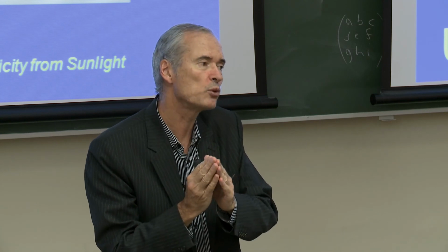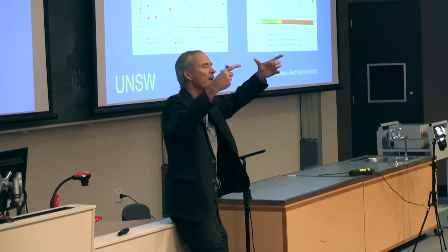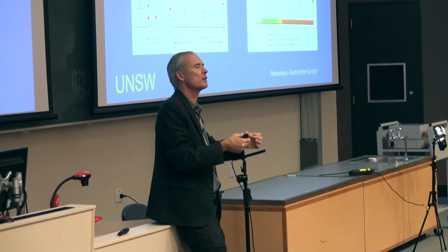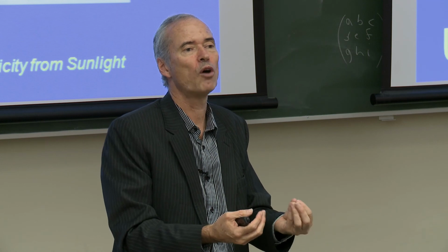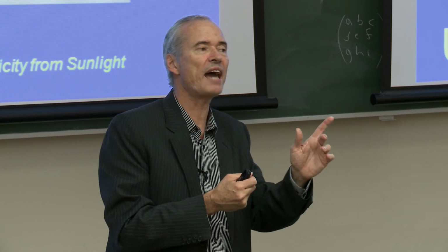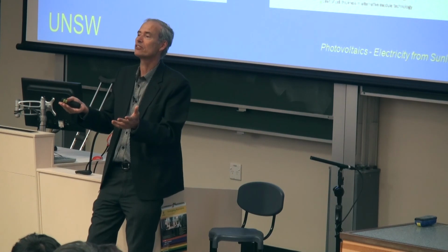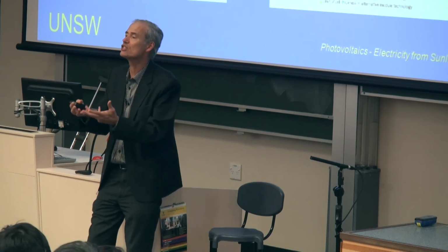And so that's caused people to actually go in the opposite direction. Instead of trying to make one huge crystal out of the whole ingot, they've now gone in the other direction and they're deliberately making smaller crystals to avoid this whole problem of dislocations propagating through the entire ingot. Now, one of the problems of doing that is that you now increase the grain boundary area to even higher than conventional multi material. And when you do that, the problem is that impurities within your silicon, when the silicon is growing, most impurities that are nasty have a segregation coefficient that's very different to the silicon, much lower.